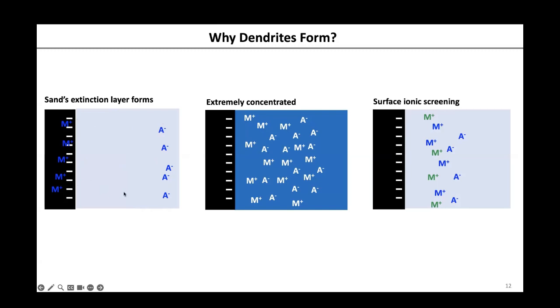Due to that vacuum of ions, any asperities on the surface will generate a high electric field. The electric field will be high because of the vacuum, and then you're going to grow those asperities into whiskers or dendrites. That's the fundamental cause of dendrite formation. In this slide, there are two solutions I want to show you. One is to use an extremely concentrated electrolyte. When the electrolyte is extremely concentrated, the ions will have nowhere to go because they're repulsed back by the highly dense presence of ions not so far away from the surface of the electrode. So that is one solution, an extremely concentrated electrolyte.